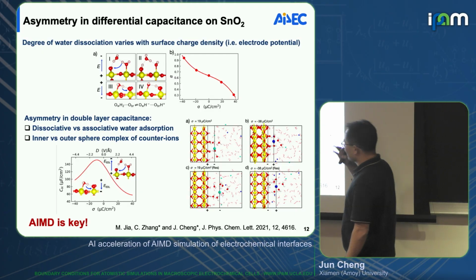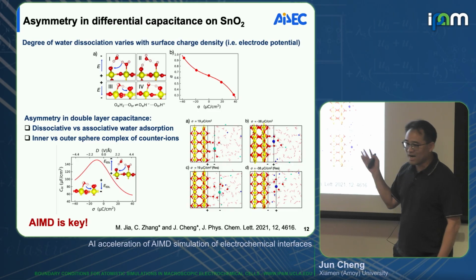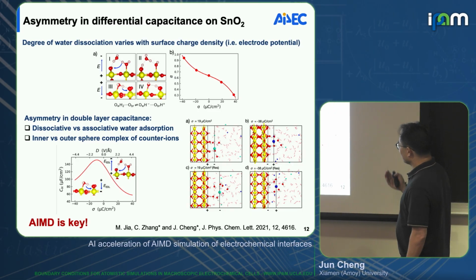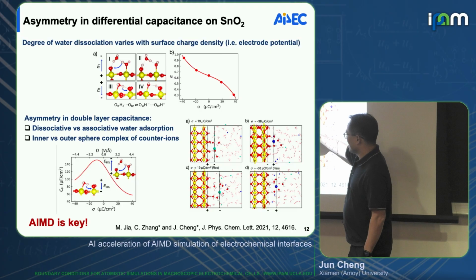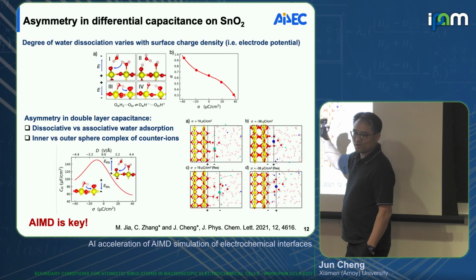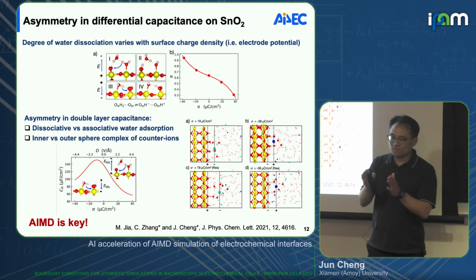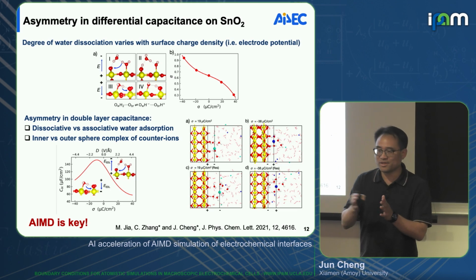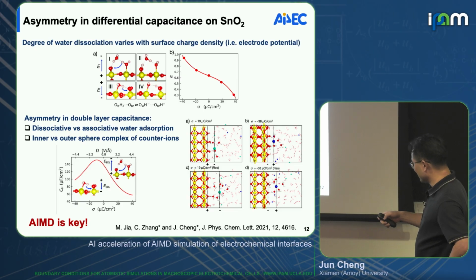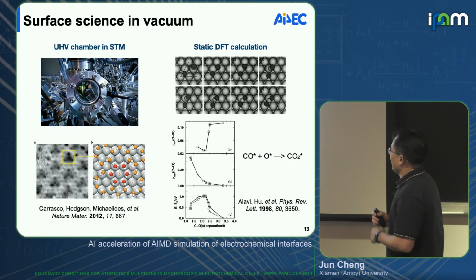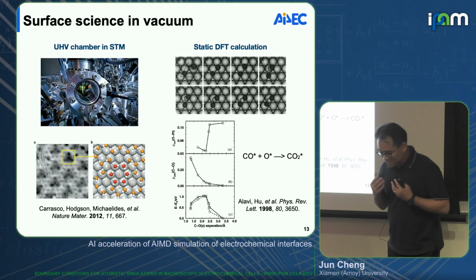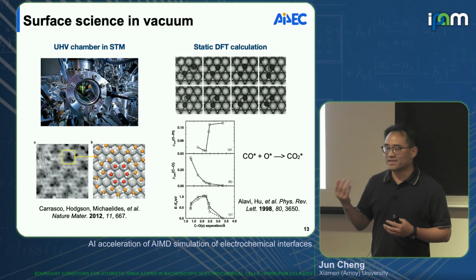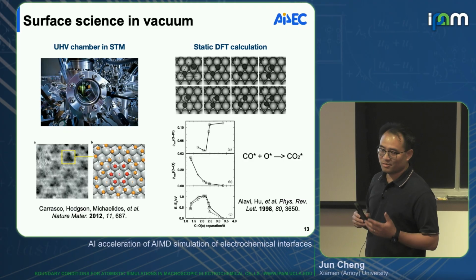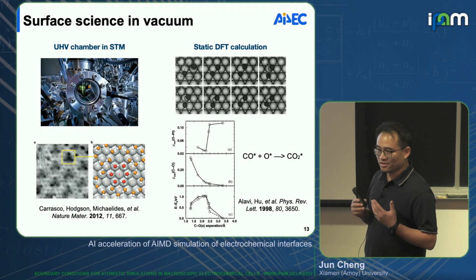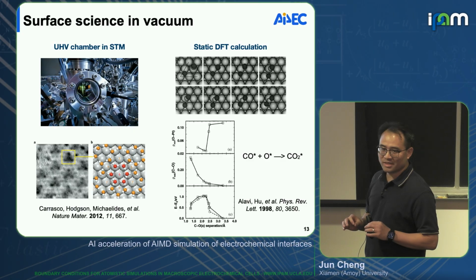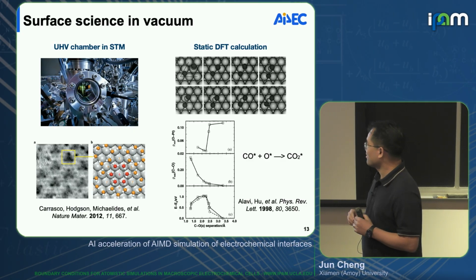differential capacitance. Again, that's even more complex because of the counter ion. Annabella also shows in her work that the ion can form so-called inner or outer sphere complexes. Then they will be located at different positions from the surface, which will surely give you different capacitance. Okay, just to quickly show, to understand the dielectric behavior of the double layer, metal and oxide is very important, taking into account both the electronic structure and also the molecular dynamics.